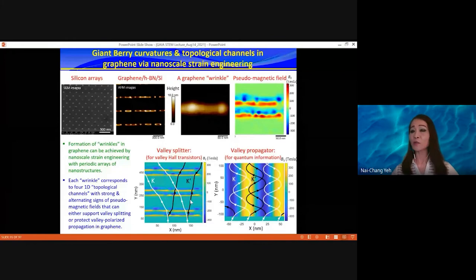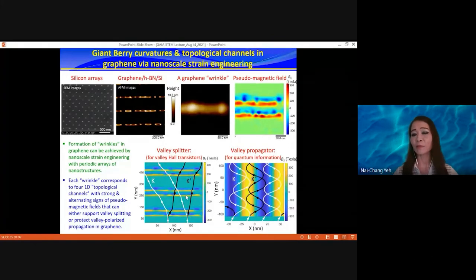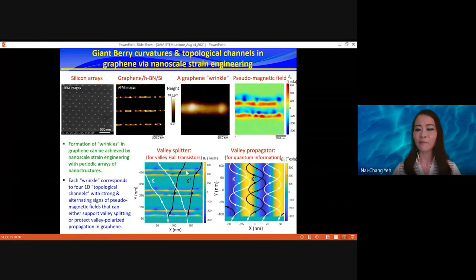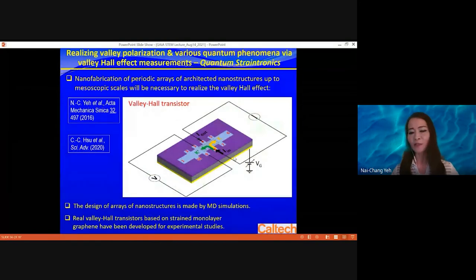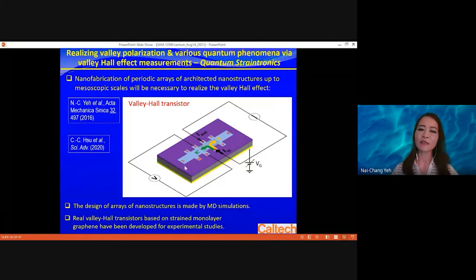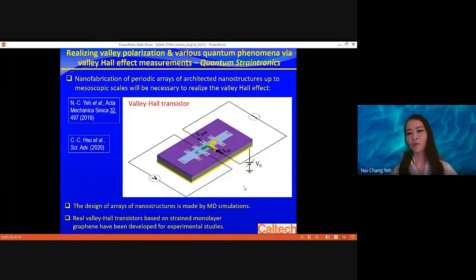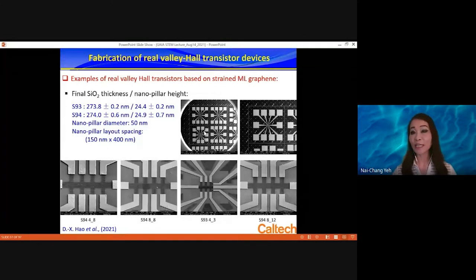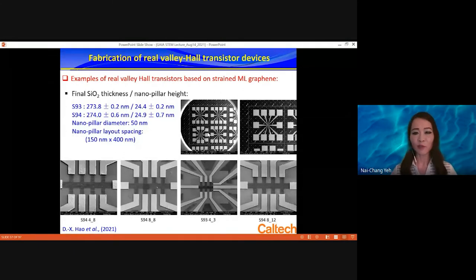This can induce novel electronic properties. If you send electrical currents perpendicular to the strain wrinkles, you can effectively split counterclockwise motion electrons and clockwise motion electrons — called K and K prime — which have unique properties. You can design these wrinkles and make a transistor device showing novel properties. We see dramatic novel properties; you can gate it by controlling the carrier density. The data showed dramatically new behavior, totally different from just graphene by itself.